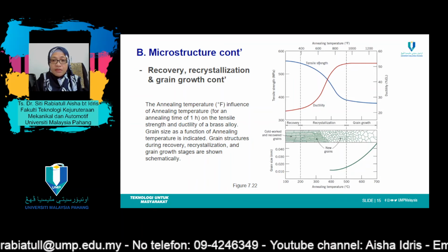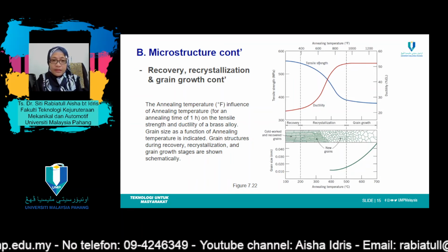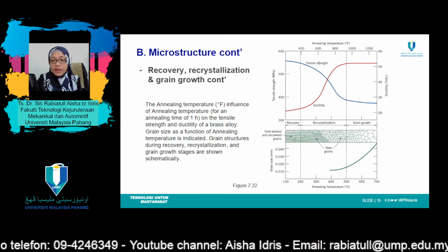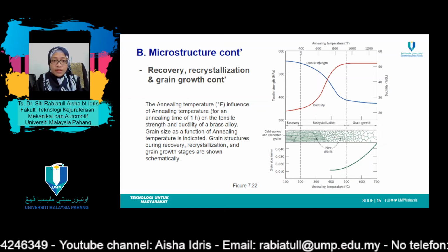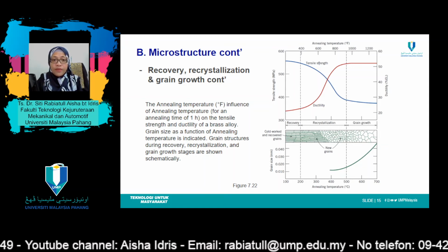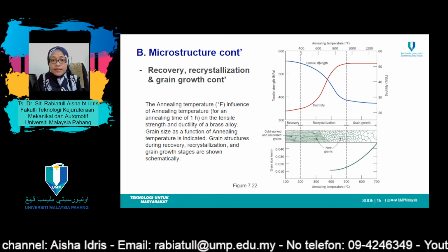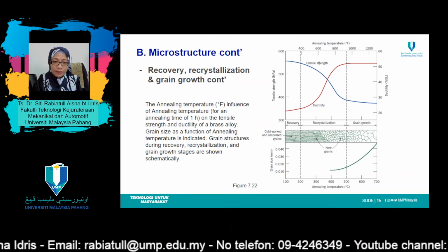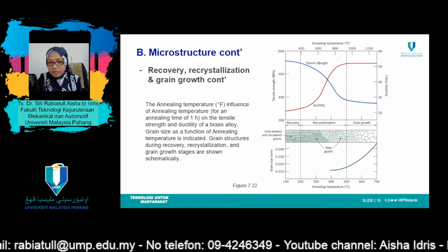Increasing the percentage of cold work enhances the rate of recrystallization, with the result that the recrystallization temperature is lowered and approaches a constant or limiting value at high deformations. Furthermore, it is this limiting or minimum recrystallization temperature that is normally specified in the literature.